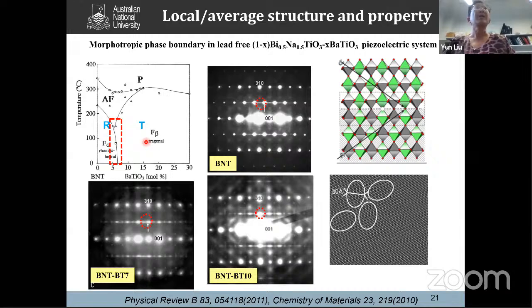Okay, so it's a very interesting fact: in the phase transition area, you don't have a gradual phase transition. What happened is your local structure gradually changes.